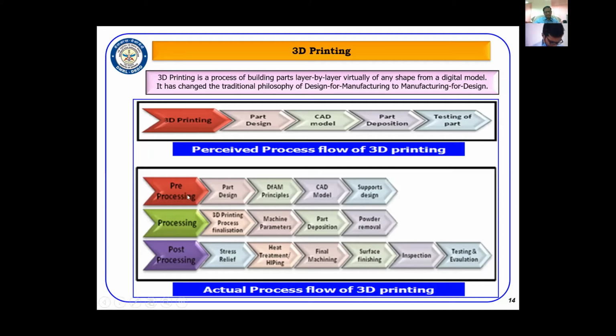Then in the post-processing, there will be a requirement of stress relief because of the very high temperatures that are involved, and then again, to improve the properties of that component, we may even adopt heat treatment processes. Many additive manufacturing components also have a certain amount of porosity inbuilt in the process. Those pores can be closed using a very high technology process like hipping, and if necessary, final machining of the component has to be carried out.